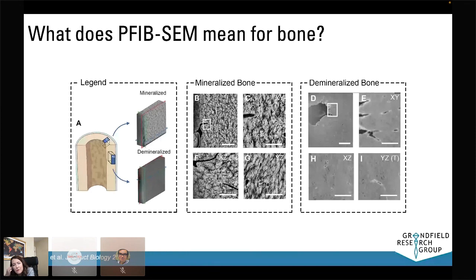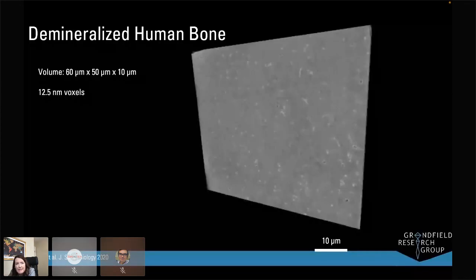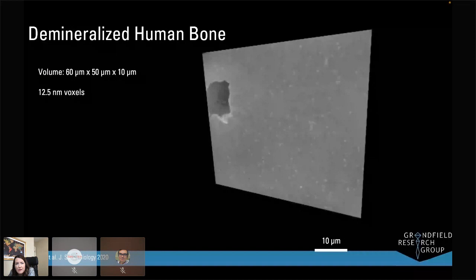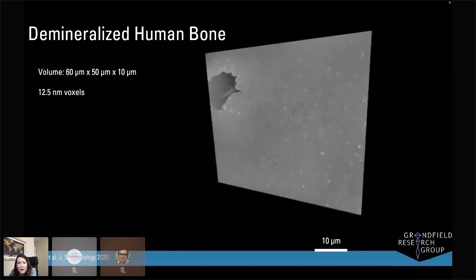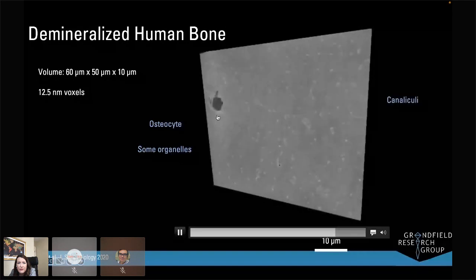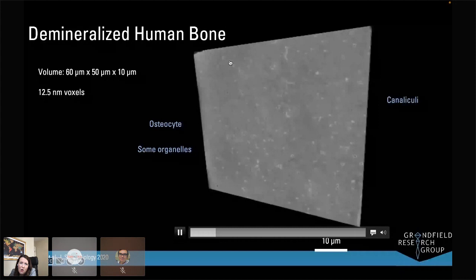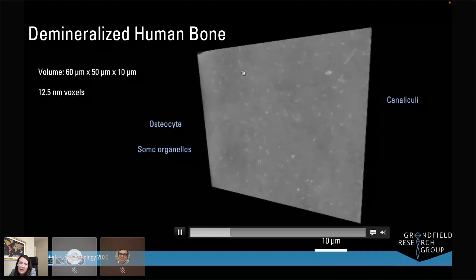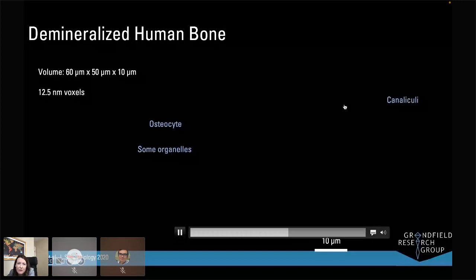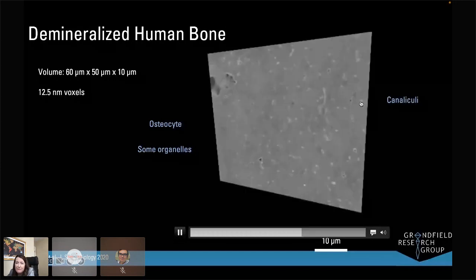In this data set, we're showing approximately 60 microns by 50 microns by 10 microns thick, and what you can start to see are some details about the bone structure. In the top left, you'll see a cell, an osteocyte, and all of these white circles and lines are the cell processes running throughout the volume of the bone structure, or the canaliculi.